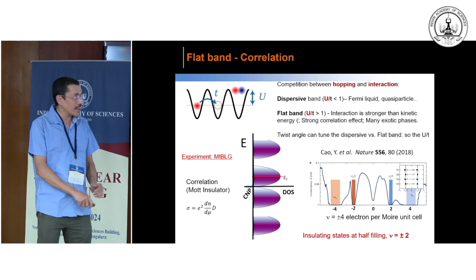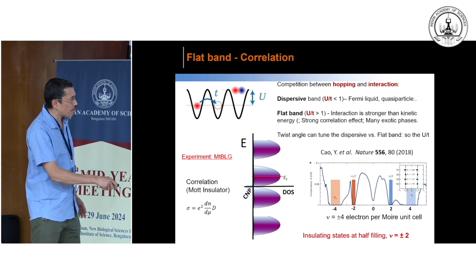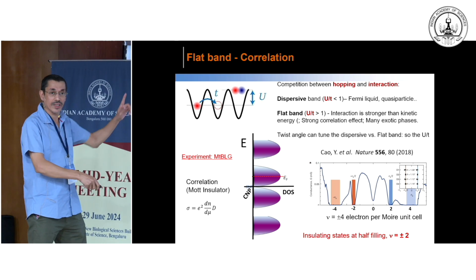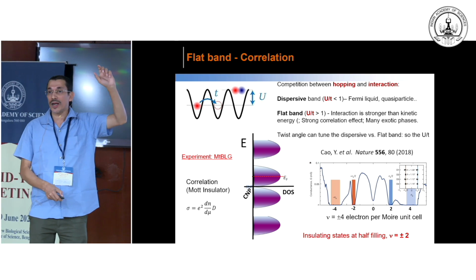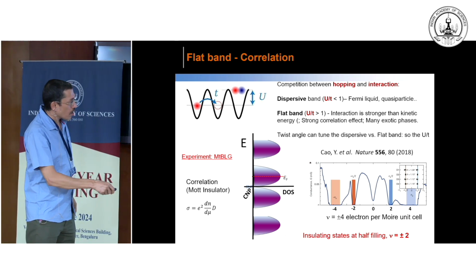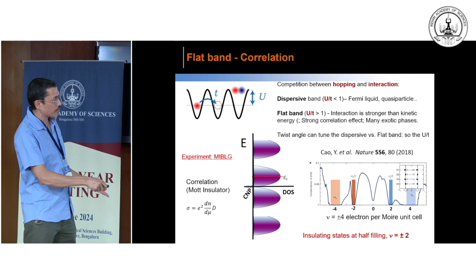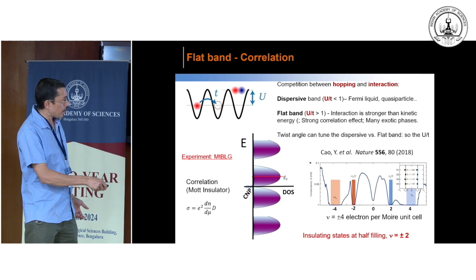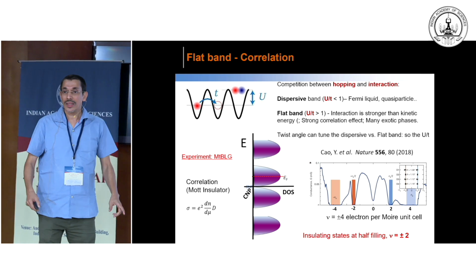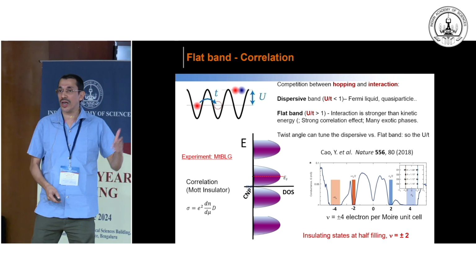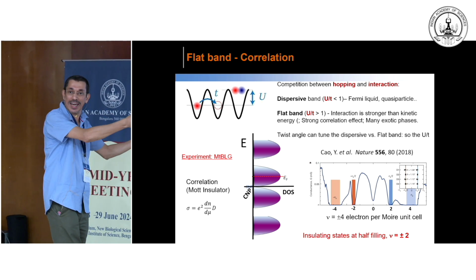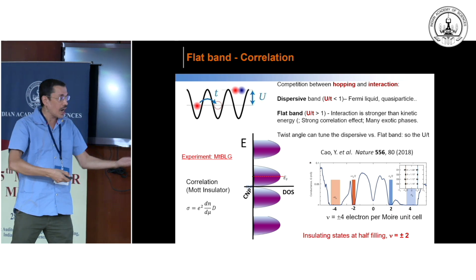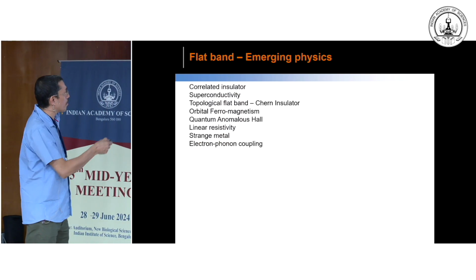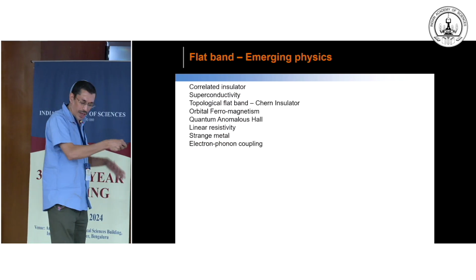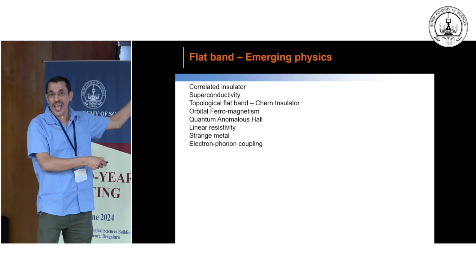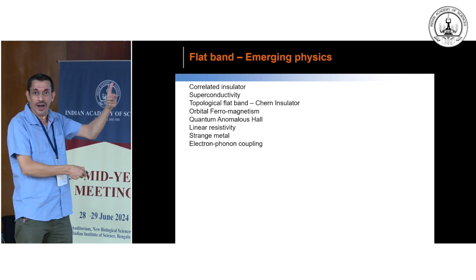And this happens exactly at half filling on both sides. Here the filling definition, again what I introduced, is the number of electrons per unit cell. So 0 is the Dirac point, 4 electrons per unit cell you basically fill up the band, or -4 you make it empty. But the interesting points are -2 and +2, which you cannot describe by the single particle picture, and this is the way the magic land of twisted bilayer graphene started, because of this work. It was followed by many dramatic, very exotic things seen on the same platform.